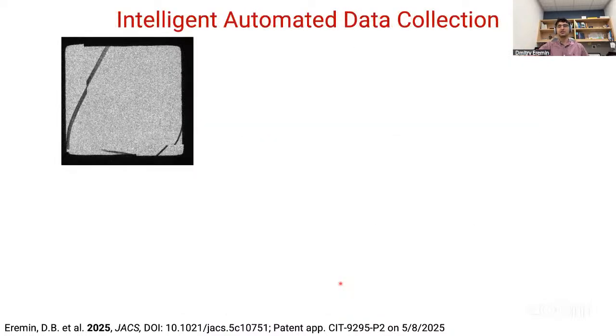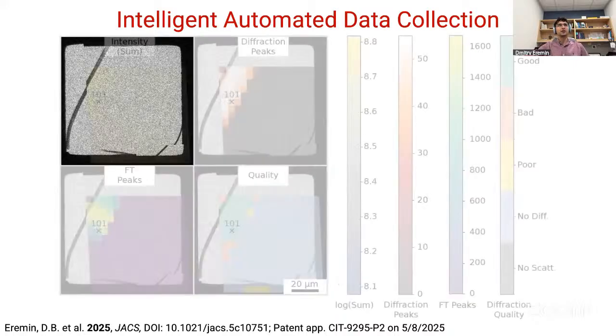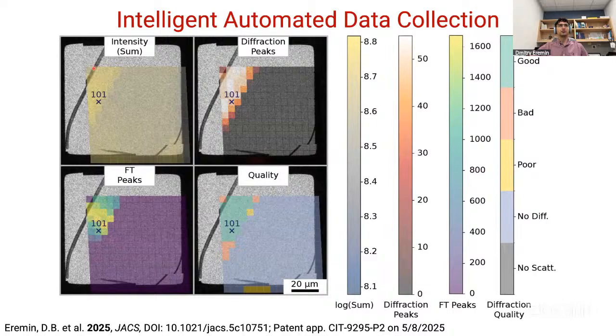So using this diffraction quality index logic, we can get several maps. We can get the overall intensity map where we know that diffraction is bright. We can count the diffraction peaks. We can then count those lattice quality peaks, and taking into account all 3 parameters, we can create this quality map. Within the quality map, we try to find where exactly we need to go and collect the data. Just a disclaimer: all the images in diffraction space are taken at a higher magnification within the microscope, with different optical settings, so they're offset from the crystal, but that's all.